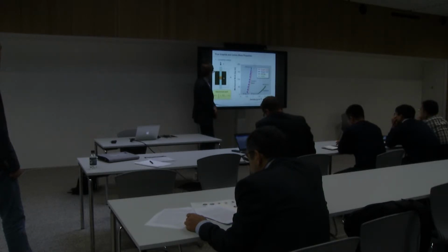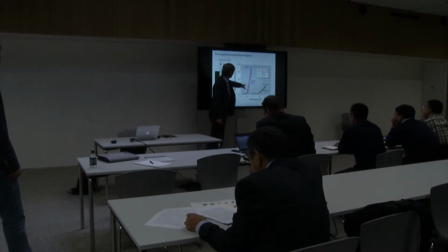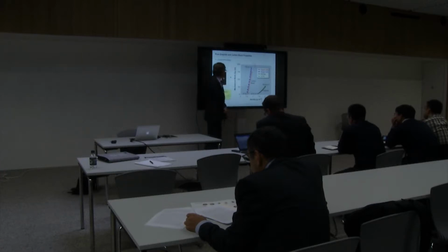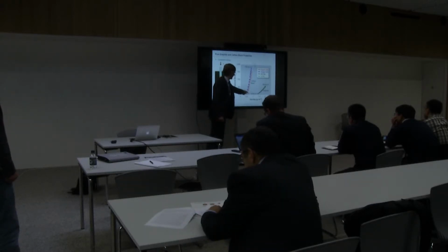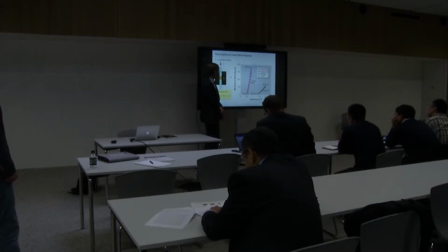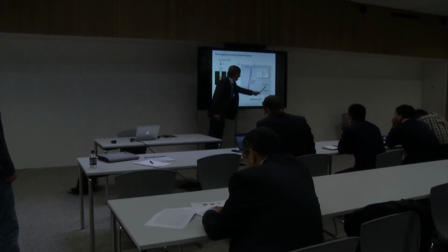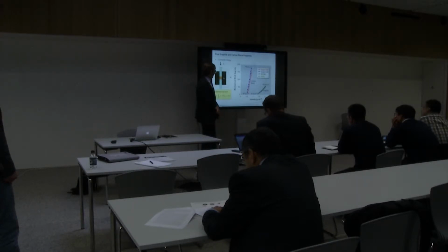This slide here shows the mechanical work that can be calculated from the sum of the incremental pressure increases and the volume changes that happen. So basically, you see here in the case of the carbon black materials that we tested, that the mechanical work sharply increases when increasing the pressure at a relatively small density range, whereas in the case of graphite, the material can be densified with a relatively low amount of work. So what you see here is basically that the graphite shows a significantly higher compressibility